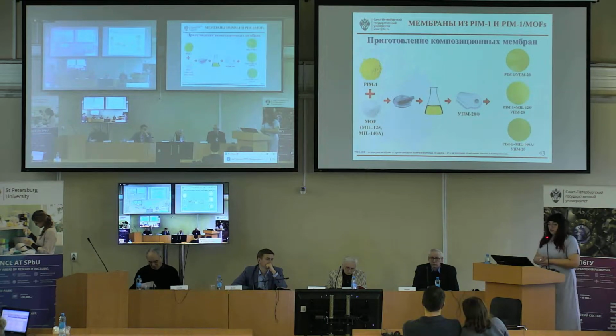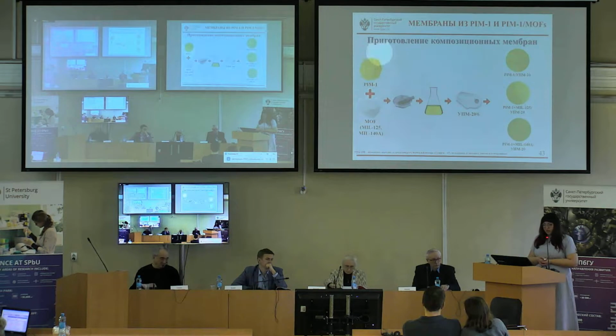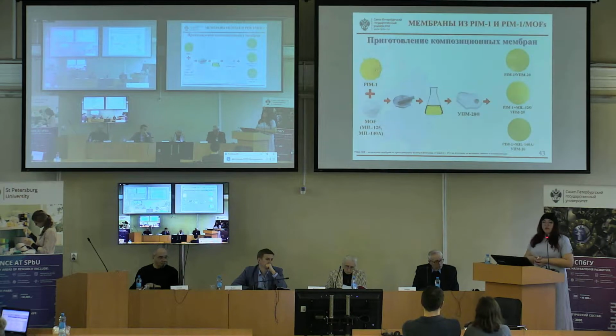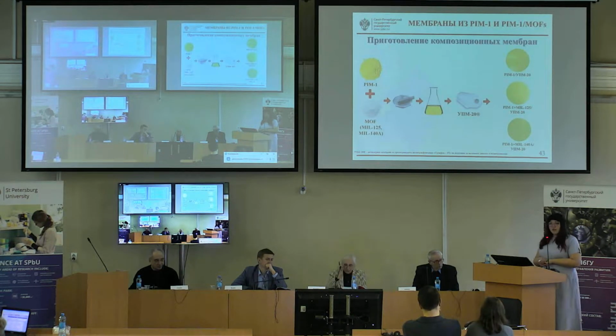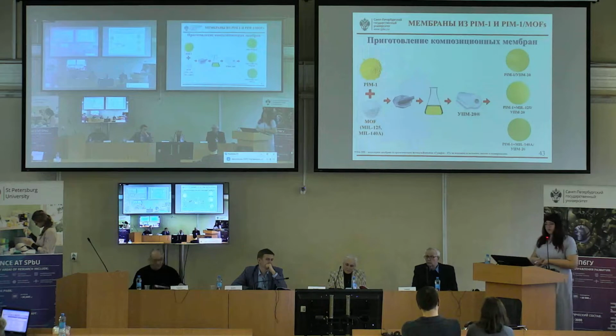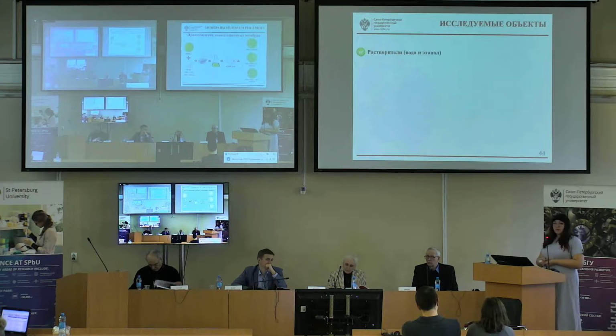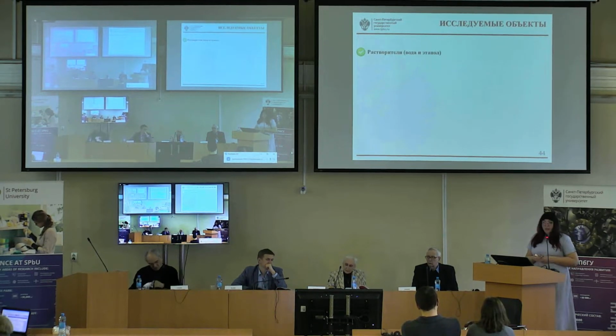The PIM-1/MOF dispersion was prepared as follows: MOF and PIM-1 powders were carefully ground in an agate mortar. The resulting mixture was dissolved in chloroform with further ultrasonic treatment. Composite membranes were obtained by pouring the resulting dispersion onto a porous industrial substrate, UPM-200, followed by evaporation of the solvent.